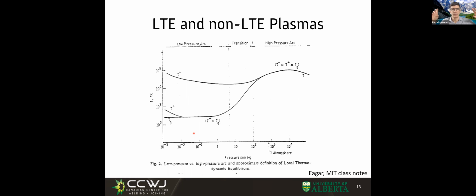And when we ionize them, now the ions and the electrons are not going to be interacting, sharing energy as efficiently as at higher pressures. So in that case, at low pressures, the electrons are moving freely and crazy and fast, and we can assign a very high temperature to those electrons. But the ions don't move very fast, right? And we would assign for the ions a lower temperature. And now it's very interesting because at the same point in space, we are assigning two different temperatures. It took me a while to wrap my head around this, right? You're used to whatever you look at with your eyes having one temperature. But if you look at a welding arc,